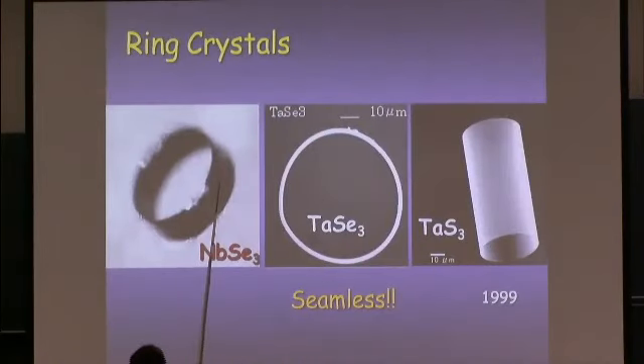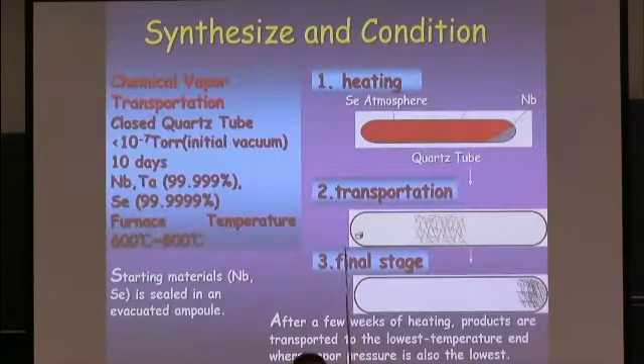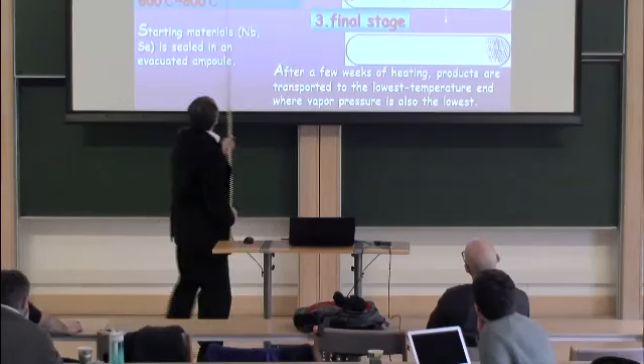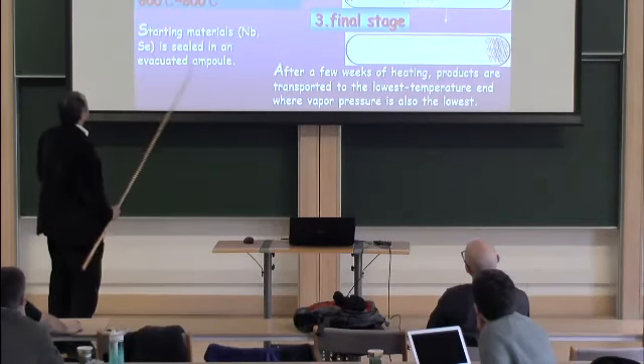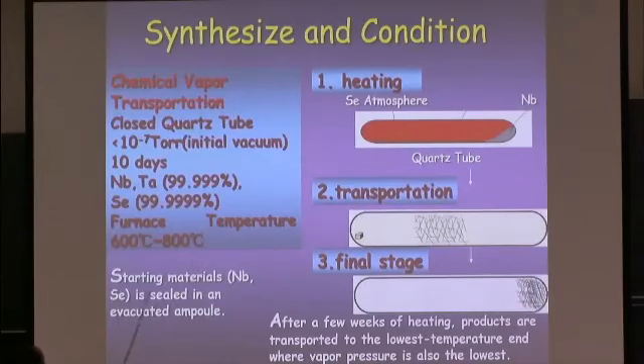We obtained the ring crystals. Typical size is about 1 micrometer to 10 micrometers. They are seamless, beautiful rings. The synthetic condition is chemical vapor transport. Starting materials, niobium and selenium, are sealed in an evacuated ampule. And after a few weeks of heating, products are transported to the lowest temperature, where vapor pressure is also the lowest.